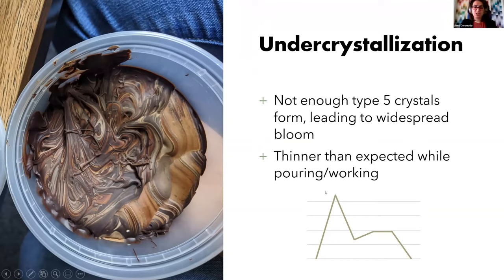So this is essentially that you went up too high, after you did the dip, you went up too high here and melted away the beta fives that you wanted. Or if you didn't do the dip step, if you just did the seeding step, you didn't seed enough. So there weren't enough of those beta 5 crystal seeds that you want, and you ended up with other crystal types growing. And the other crystal types cause this bloom. This is kind of a combination of both fat and sugar bloom.